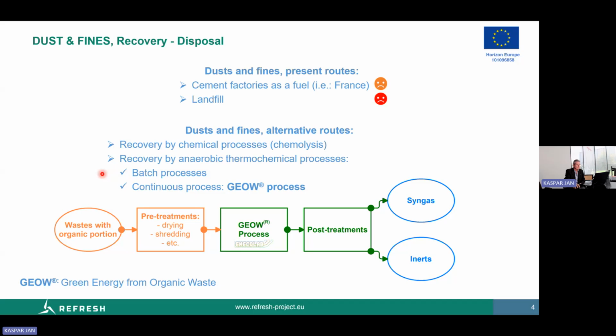So essentially what we do in our job is to have some waste. Of course, the process is tuned in this project towards our dust and fines, but could be possibly any kind of waste which has some significant organic portion. We pre-treat and move it into a reactor, which is a pyrolysis reactor, and eventually there is a post-treatment. The main product which we are interested in is the syngas. The reason is that production of oils or whatsoever normally leads to complex mixtures, which for application may need to be separated.